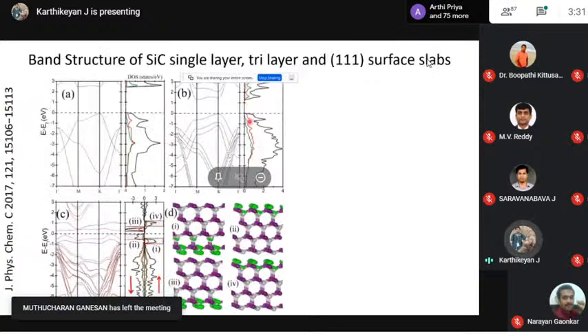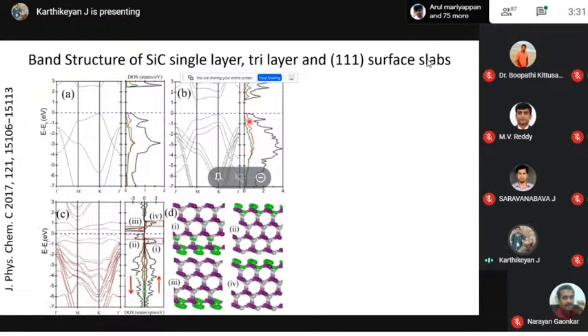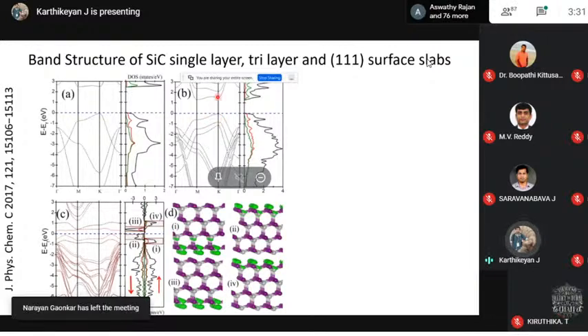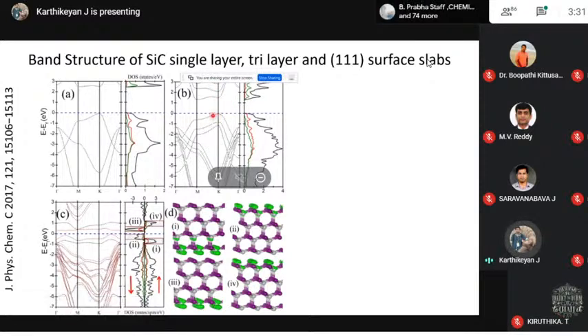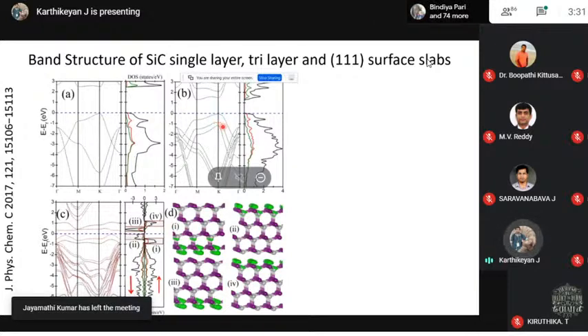Before studying the lithium interaction with these nanoslabs, let us study the band structure. We calculated the band structure for a single layer of silicon carbide, which has a very high band gap. Then we also tried 3 layers. Here for 3 layers, you can see there are 3 bands coming from 3 layers and 3 conduction bands, and the band gap is slightly reduced. This one is coming from the top layer, this from the middle layer, and this from the other side of the layer. So these are coming from the 3 layers of this graphitic silicon carbide.